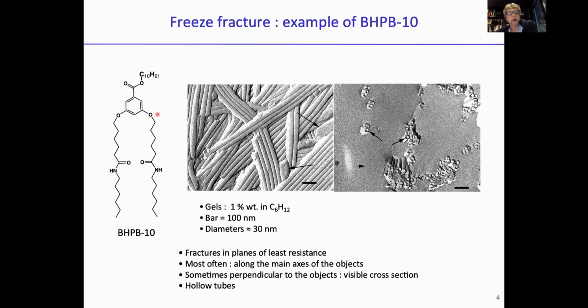So this is for the compound BHPB-10, and you can see the gel is cleaved, and the mean plane of cleavage contains the main axis of the objects, which are mostly cylinders, like you can see on these pictures. The diameter of these objects is about 30 nanometers. And here you can see the remaining amorphous solvent. Most of the fractures occur in a plane that contains the axis of the object, but in 1% of the cases, some fractures occur perpendicular to the axis of these objects.